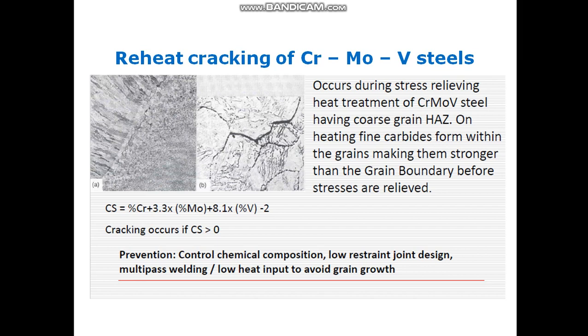First is to control the chemical composition. It means chrome, moly, and vanadium. The lower the chrome, moly, and vanadium percentage, the lower the risk of reheat cracking. Then low restraint joint design, because if there are more mechanical restraints, then under the restraints the stresses are very severe. Then multi-pass welding or low heat input to avoid grain growth, because grain growth has to be controlled, as reheat cracking problems occur particularly due to coarse grain size in the heat affected zone.